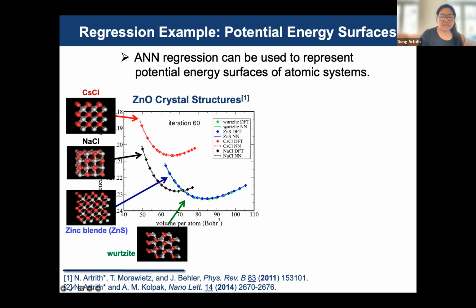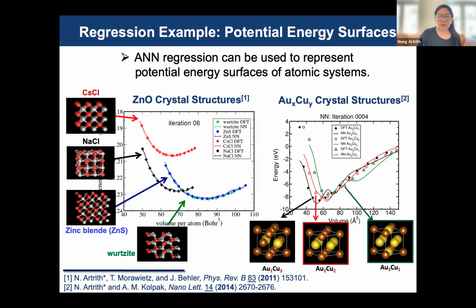As you can see, the DFT reference data is in symbols and also the neural network training in solid line. So all crystal structures or all phases of the neural potentials predict in good agreement with the DFT reference data. And also another type of model, we have also a complex copper gold alloy with the crystal structures. Here there are 3 types of the crystal structures of the copper gold. So the DFT reference data is shown in symbols and also the neural network predictions after training in the solid line. So again, after optimization and minimizing the weight parameters, and then really minimizing error, we can get the neural network potential to predict DFT results accurately.